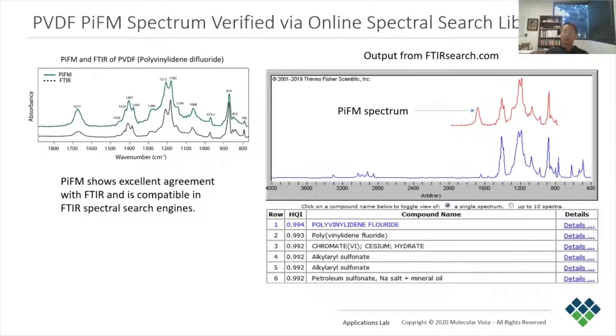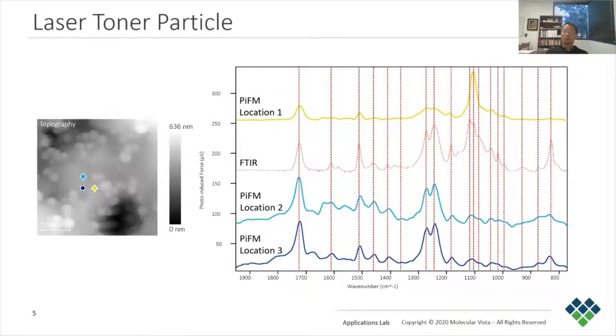For this slide, we took a PIFM spectrum of a homogeneous piece of polyvinylidene fluoride and used an online FTIR database to look for a match. The first match with the highest quality index is polyvinylidene fluoride. Since PIFM has excellent sensitivity and can acquire good spectra from defects as small as 20 nm, it can identify unknown defects with good confidence.